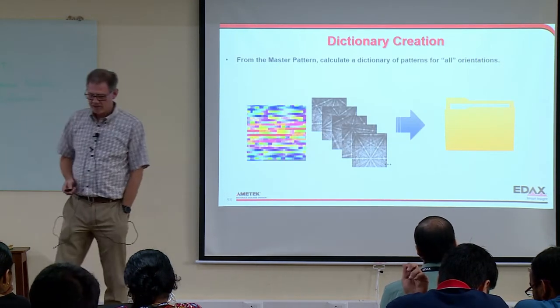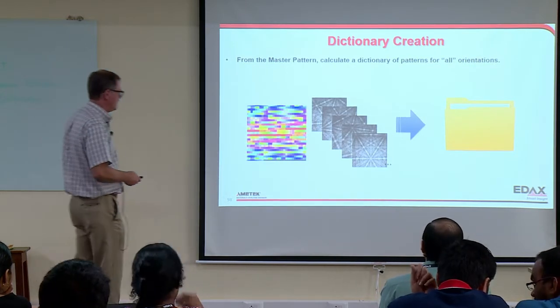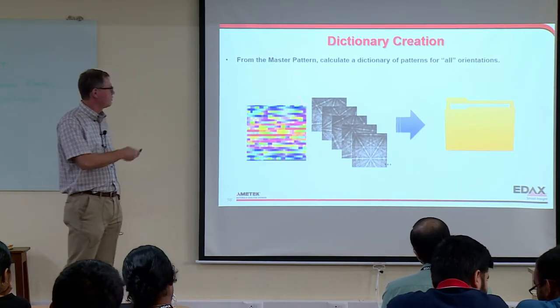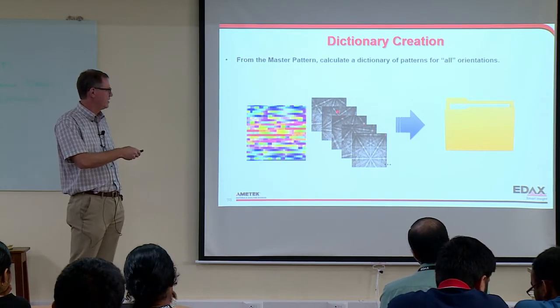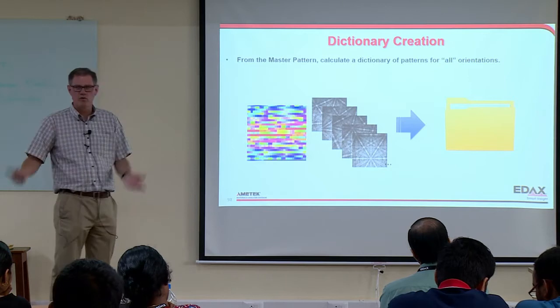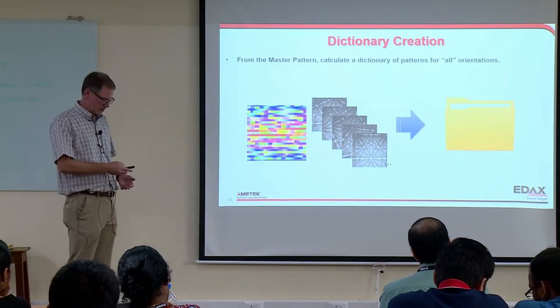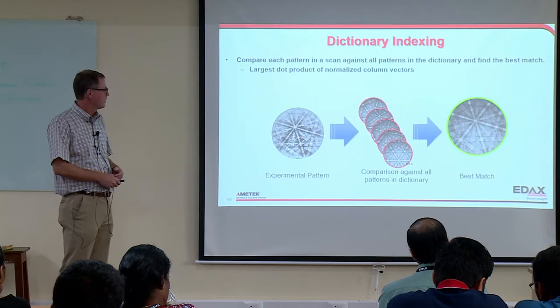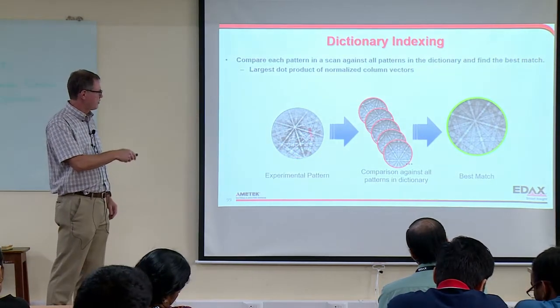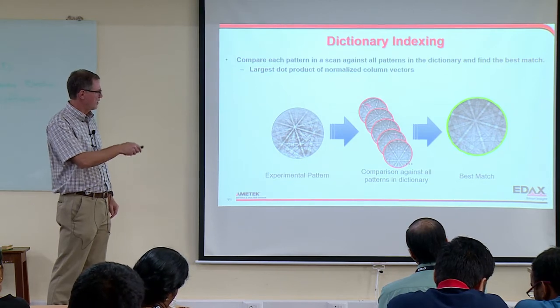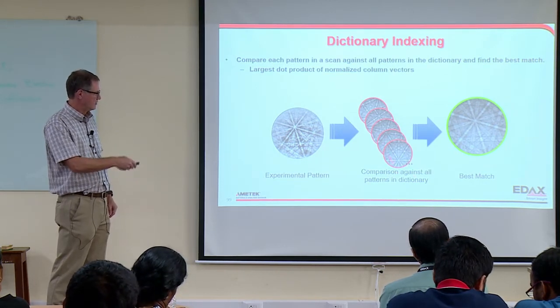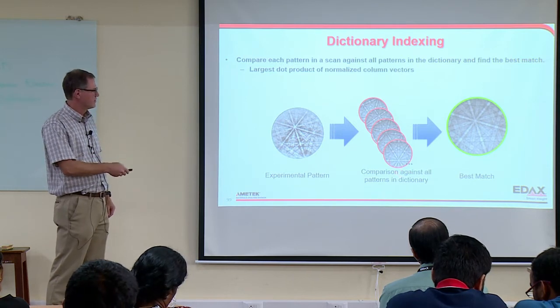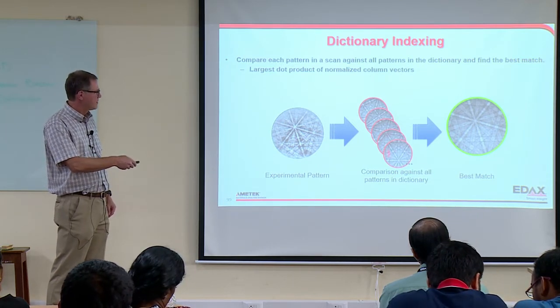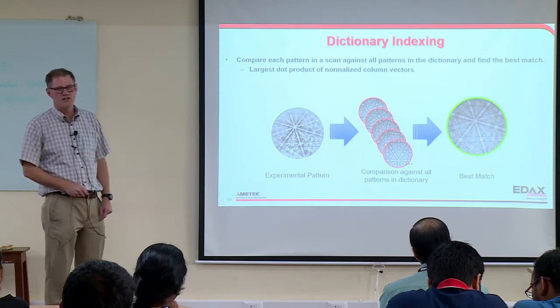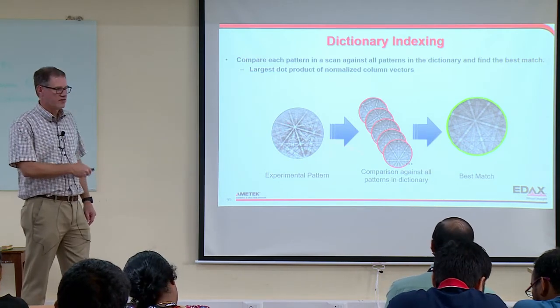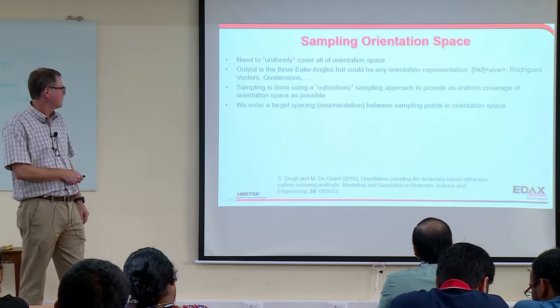So what we want to do is create a dictionary. The idea here is we want to cover all of orientation space and calculate an individual simulated pattern for every orientation in orientation space. We save those patterns onto disk. And then we take our experimental pattern, and through a dot product, we compare it against all the patterns in the dictionary. So this is thousands, tens of thousands. And we find the one that matches this pattern the best. So we find a best match. You can see this is very computationally intensive, but it has its advantages.